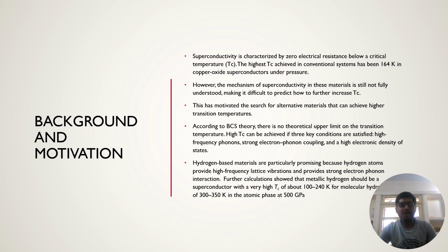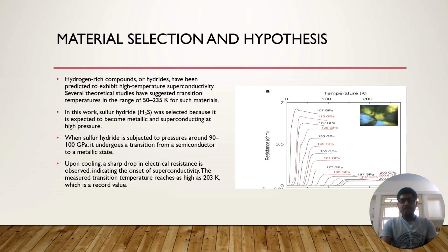Hydrogen is particularly important in this context because its low atomic mass leads to very high phonon frequency, and it enhances electron-phonon interaction. Theoretical studies predict that metallic hydrogen could exhibit superconductivity near room temperature under extremely high pressure. This motivates the search for suitable materials. Instead of pure hydrogen, hydrogen-rich compounds known as hydrides provide a practical approach. Among these, sulfur hydride becomes particularly important because it can mimic the properties of metallic hydrogen under pressure.